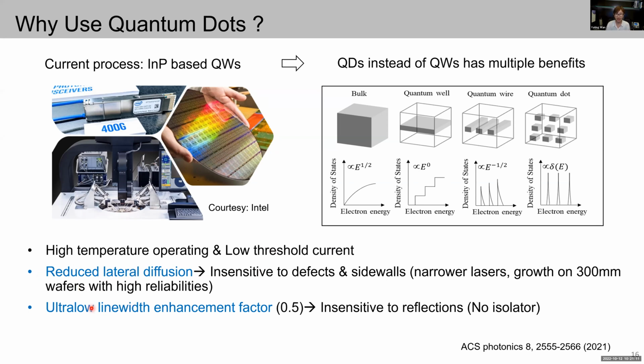And finally, the ultra low linewidth enhancement factor, or what we call the alpha factor. This can reduce the sensitivity to reflections, so people don't need isolators that are bulky and expensive. These last two points are very important, and I'd like to especially emphasize them.